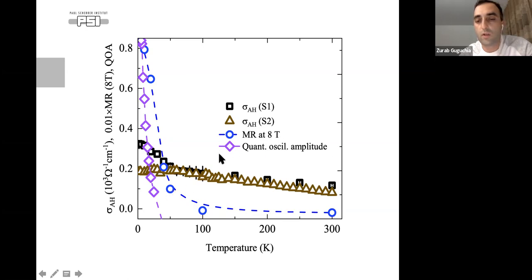Also the quantum oscillation amplitude, which reveals the Landau quantization in this system that's related to this Chern gap, also increases below about 25 Kelvin or so. So while the real magnetic ordering is near room temperature, these interesting topological features appear only at low temperatures. The idea was to see whether there is some additional magnetic transition at low temperature, and what's really going on with this anomalous Hall conductivity.